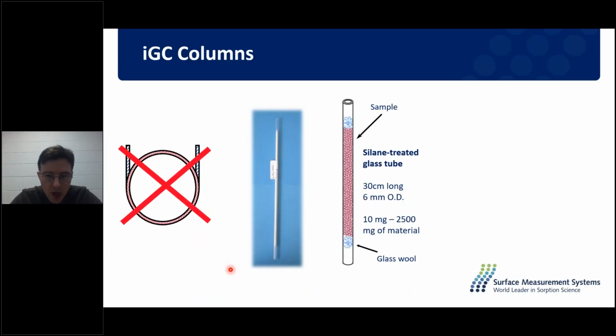So this is all of the work a user would really have to do in sample preparation. It's a very simple scenario of taking a silanized glass column. You then put some glass wool into the bottom of this column, and then we pack our sample within. Anywhere between 10 milligrams to 2,500 milligrams would be appropriate for this sort of experiment. And it really does depend on the surface area and the activity of my sample. So a porous material such as a MOF or a zeolite would need a very small amount of sample due to its high surface area and high activity. Something with a low surface area, something like a fiber, would need a lot more of my sample. So I am maximizing the interaction between my probes and my sample.